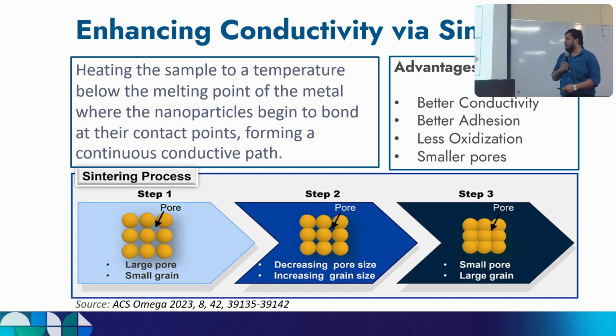Also, there are pores, because since we are using nanoparticles, they are in an array like this when printed. So there are small pores between each particle in the neighborhood. When we heat the printed electronics, those pores become reduced because of the better adhesion. So the pore reduction helps with reliability, because these pores are the thing that causes mechanical breakdowns in circuits. We will look at that down the road. Yes, that is mainly my research.